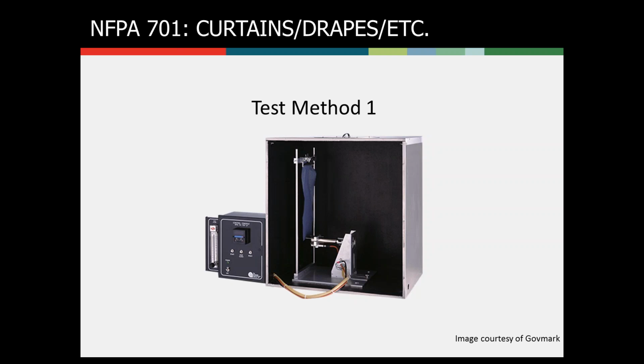It's tested inside this small little box that you can see. It's about 2 feet by 2 feet. And the specimen is 6 inches by 16 inches long. It's hung vertically. And it's ignited there by about a 1.5 inch premixed methane burner. And it's kept there for 45 seconds.